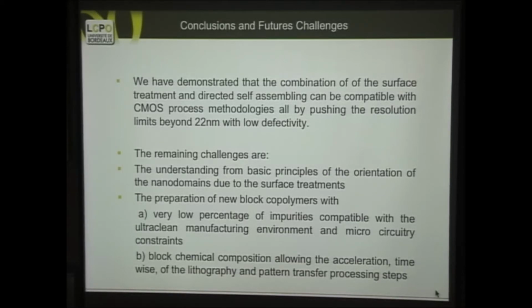And this is the challenge we are facing now from the materials point of view, to go further and make materials that make these patterns just by spinning down the film and then revealing the nanostructure that we want. So, the proof of principle is that we can, yes, go below the 22 nanometers, which is the ITRS, the silicon roadmap, the silicon nanotechnology.